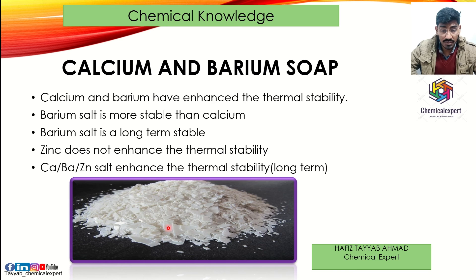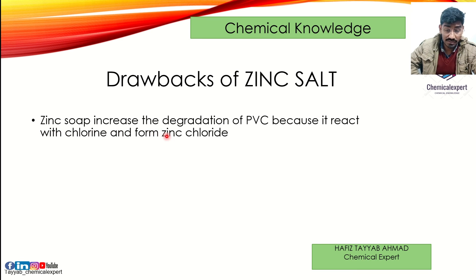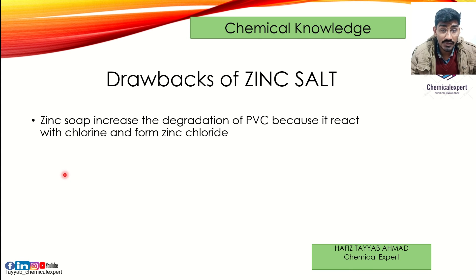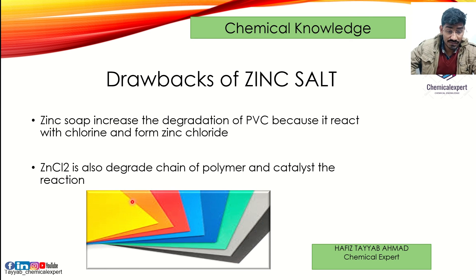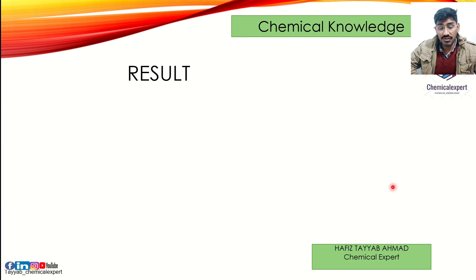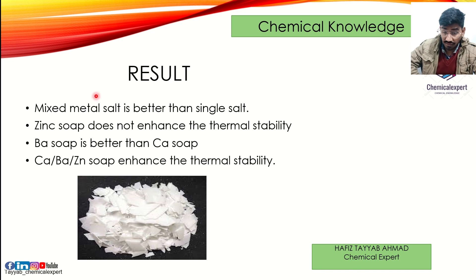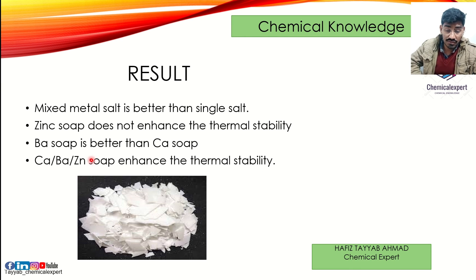The major drawback of zinc salt is that it enhances the degradation of PVC — zinc reacts directly with chlorine and forms zinc chloride. Since PVC contains chloride, zinc mixes with it and produces zinc chloride, which is not a good outcome. Zinc chloride also acts as a catalyst and further degrades the polyvinyl chloride chain. The final result: a mixed metal salt is better than a single salt. Barium is better than calcium alone, and calcium-barium-zinc mixed salt is the best option for thermal stability.